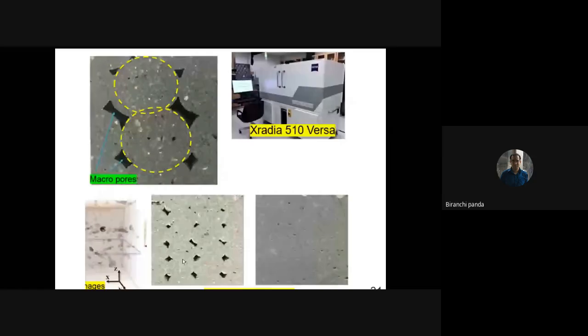So it means that printing parameters alone are not responsible for producing quality printed structures. We can also play with the material as well as with the printing parameters. The first picture represents when the material is very stiff and you are still using a circular nozzle. In the second case, you can see that the material has been slightly modified so that with the load of the layers, these pores have been reduced. But apart from all these things, if you simply replace the circular nozzle with a rectangular nozzle, you can further minimize the pores, as you can see in the last picture. So this is all about the effect of nozzle shape and size.